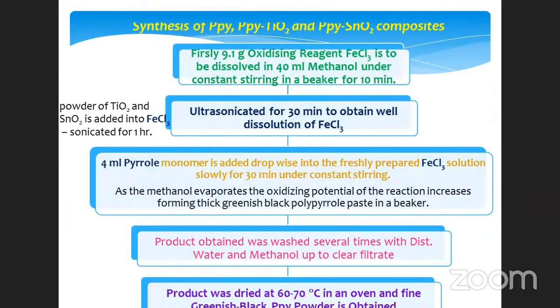First of all, a beaker is taken. In that beaker, 40 ml of methanol is taken. Into that, FeCl3, which is the oxidizing reagent, is dissolved. It is sonicated for 30 minutes. Why is sonication necessary? To have a homogeneous solution, so that polymerization is efficient. Then, after sonication, 4 ml of pyrrole is taken into an injection syringe and poured into the reagent drop by drop to have polymerization.